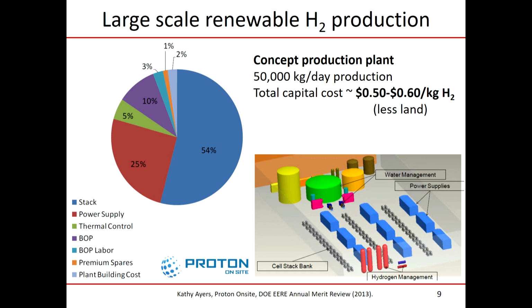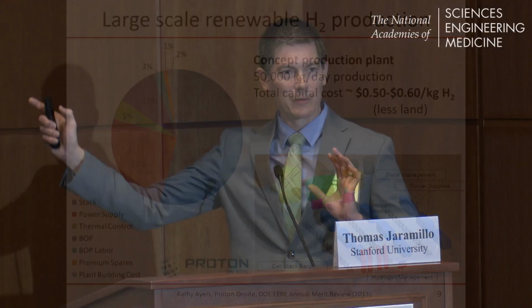And you can see that there are a lot of levers here, and there's not a single lever alone that is going to get us to where we need to be. But the biggest chunk of the pie is in the stack itself, the 54% you see, and a big chunk of that is the precious metals. They use platinum and iridium catalysts. Now, they're projecting 50 to 60 cents per kilogram of hydrogen. This is like their forward-looking models with additive manufacturing and reducing precious metal content and all these good advances.